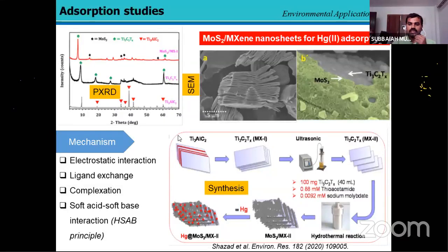which was applied for the development of molybdenum sulfide on the surface of MXene by a hydrothermal method. Then we confirmed that the molybdenum sulfide was intercalated between the layers rather than deposited on the MXene phase by XRD results. Then the mechanism was explained: mercury was absorbed on the MXene phase through electrostatic interaction, ligand exchange, complexation, as well as soft acid, soft base interaction. Since molybdenum sulfide has a sulfur moiety which is a soft acid, the soft base of mercury will interact easily, following the HSAB principle.